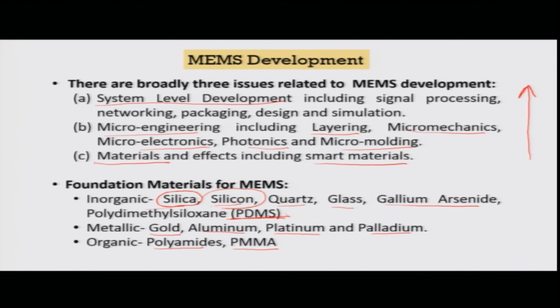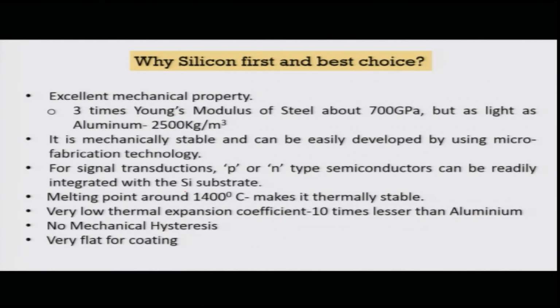silica and silicon. Now, why is it that silicon is the first and best choice for us? It is because it has excellent mechanical property. It has 3 times the Young's modulus of steel, about 700 GPa, but it is as light as aluminum because its density is only 2500 kg per meter cube. So, it is an excellent material at a smaller scale. It is mechanically stable and can be easily developed by using microfabrication technology. We will just touch on this microfabrication technology in a short while.